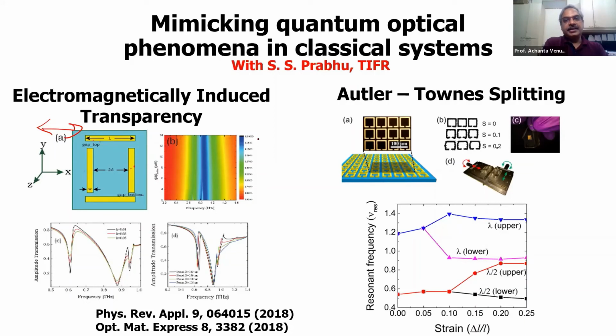So when you have a two-level system, for example, with a finite lifetime, like finite line width, and if you have a continuum system, where all these energy levels are possible, and you have very short lifetime, so this is in lambda. The broader the spectrum means you have very short lifetime, and narrower the line width means you have long lifetime. Right? When you have a system like this, where a two-level system is in resonance with a continuum, your line shape gets modulated, and you get an asymmetric line shape called the Fano line shape.